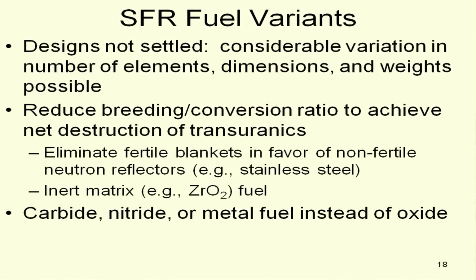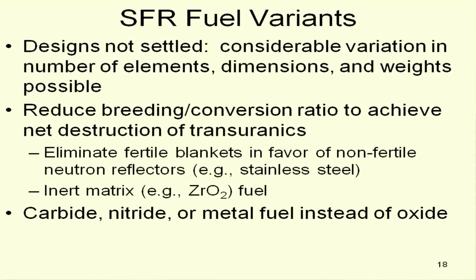So what's going on? You don't want to be breeding more plutonium than you're consuming if you're trying to destroy actinides. So now there's a lot more look at reducing the breeding or conversion ratio. Instead of like 1.2, make it 0.75 or 0.5 by eliminating these fertile material blankets that I mentioned in favor of non-fertile neutron reflectors that just bounce back a neutron. And in the limit, going to an inert matrix fuel. Instead of having UO2, have plutonium in zirconia or yttria or some other thing. These are not without challenges because as you take the U-238 out of these systems, you start to encounter control and safety issues. And there are likely limits to where you can go with this.